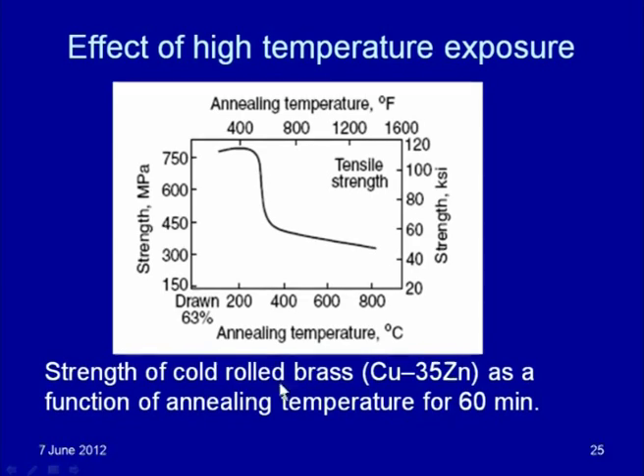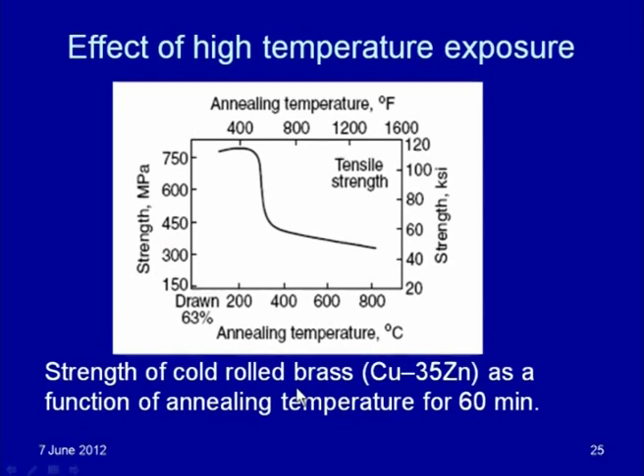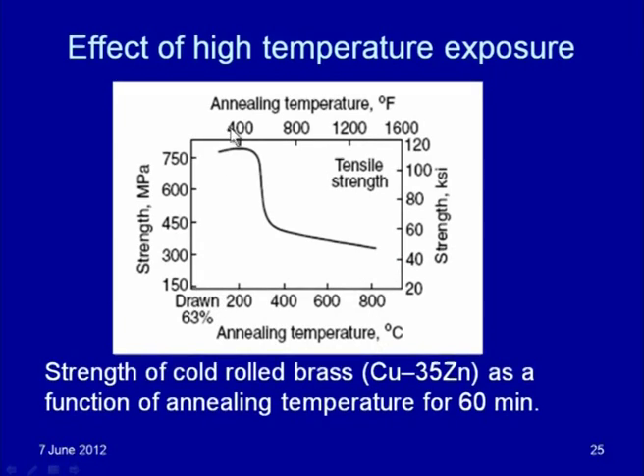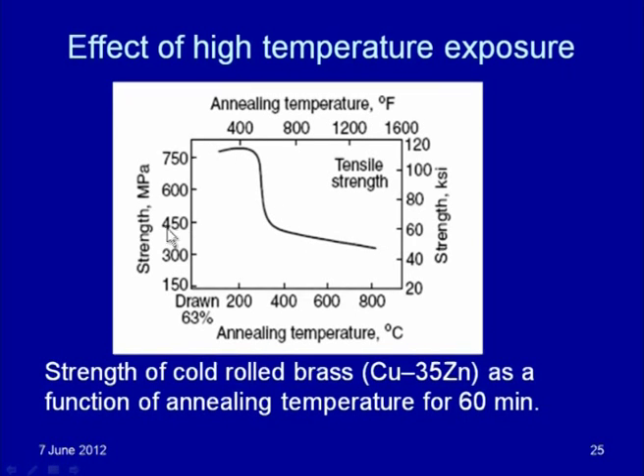For example, consider cold-rolled brass with copper and 35% zinc — how its strength is affected by annealing temperature when the exposure is given for 60 minutes. When the material is in the cold-worked condition, its strength is very good, around 750–800 MPa. With an increase in annealing temperature, there is a sharp drop in strength, mainly attributed to the formation of newer grains of larger size. This grain coarsening is mainly responsible for the deterioration in strength.